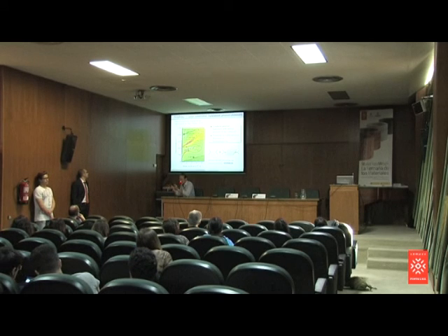What you see here is the dispersion of a graphene plasmon when graphene is on silicon dioxide. And then the point is silicon dioxide has optical phonons. They are polar phonons, and they have frequencies here and here. And this is how the graphene plasmon should look like on a completely inert material, no? And it doesn't. It hybridizes here, because here the graphene plasmon excites a phonon in the substrate, and here the graphene plasmon excites a phonon in the substrate. And what you get are coupled oscillations of phonons and electrons all together.